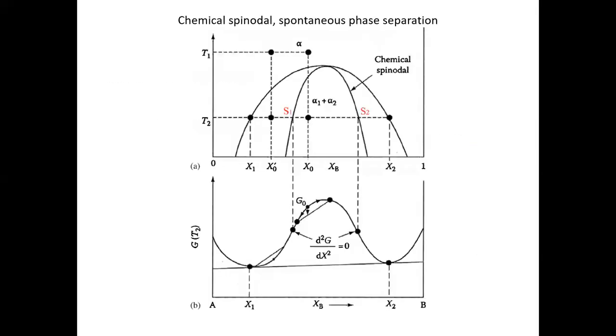So how do we define the miscibility gap? Typically the miscibility gap is defined as the outer dome. That's just from my understanding, but I think there might be a different way of doing this. And then the inner dome or the inner envelope is typically what we call the chemical spinodal, which means that if you're within the inner dome, you have spontaneous instability. So you're never going to have any metastable state. If you prepare the system within this inner dome, there's no way that you can ever stay as the mixing state when you lower the temperature.